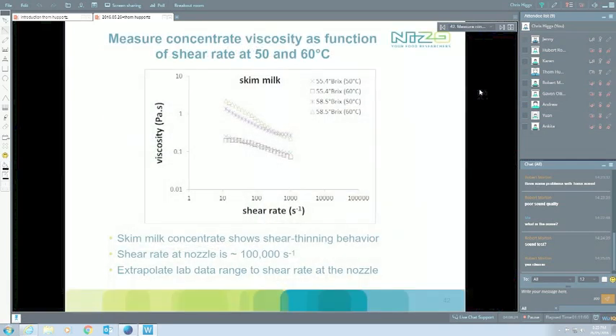We could make skim milk concentrates at different solids contents and measure the viscosity of that. As we see, it's very much shear thinning, as we always expect to see, and viscosity decreases with increasing shear rate. The question is then, of course, what is it in the nozzle? Because with our rheometers in the lab, we can go up to a shear rate of about 1000 per second. If we want to know what is happening in the nozzle, we're pretty much at 100,000 per second.